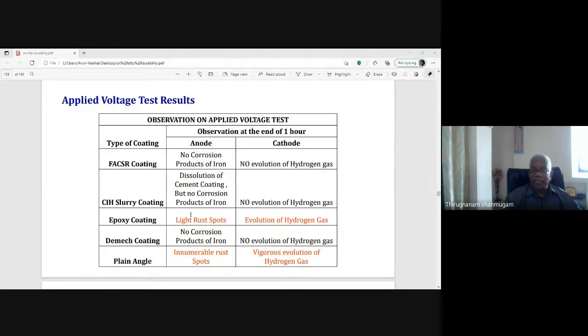Similarly, if epoxy coating is provided, this is restricted to light rust, and a light evolution, but still there is an evolution of hydrogen gas. But for other coatings, with the FACSR coating or CIH slurry coating, there are no corrosion products of iron at the anode level, and no evolution of hydrogen gas at the cathode level, as per the previous indications.